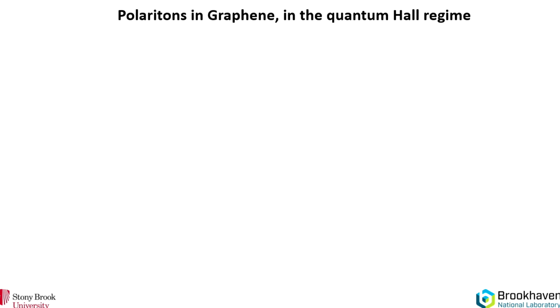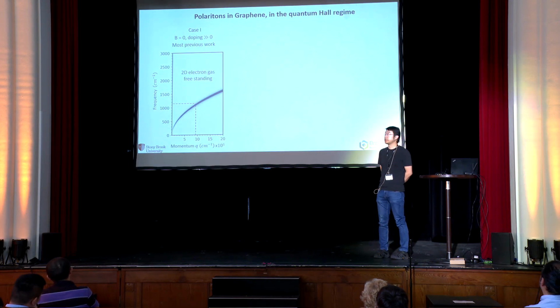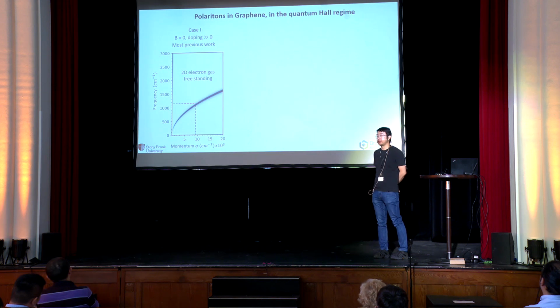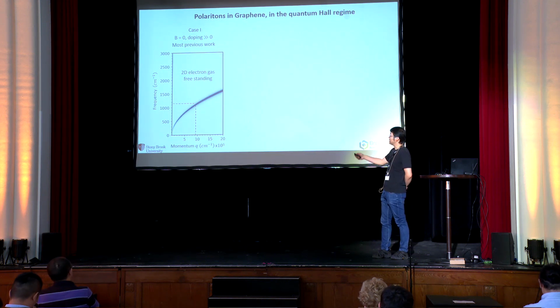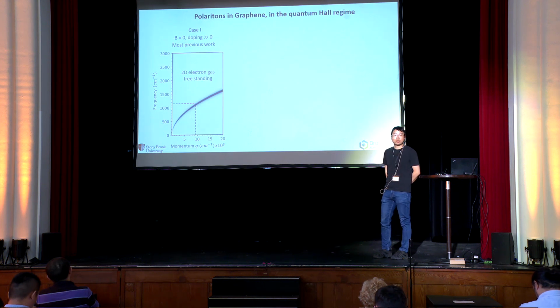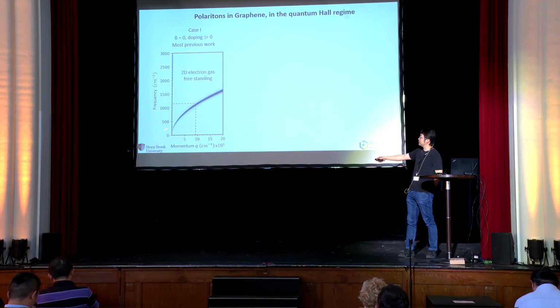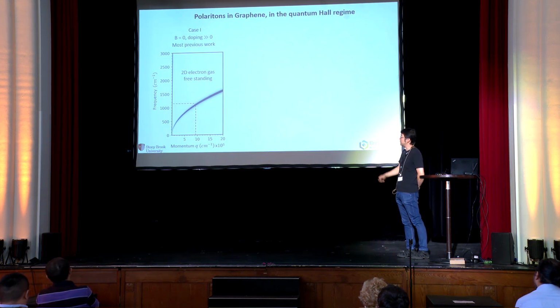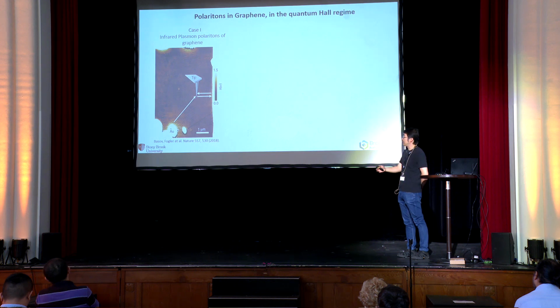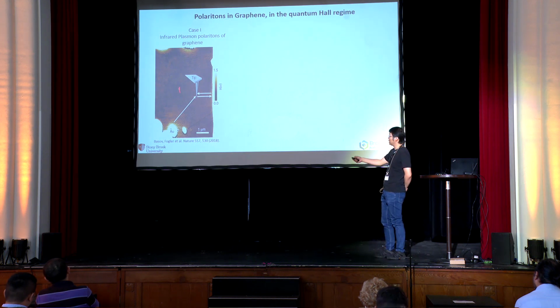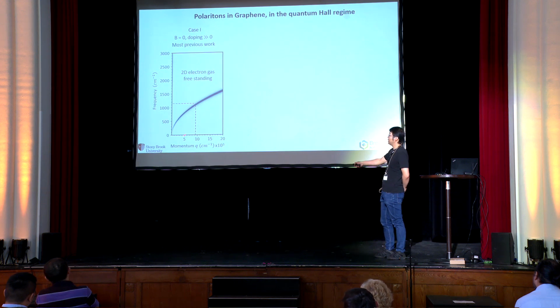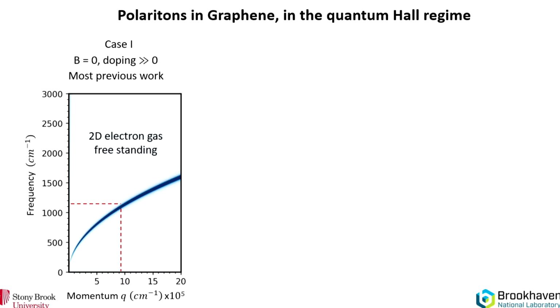So polaritons, we have learned a great deal in the first case of polaritons. I characterize them in 3 different cases, not necessarily true, but this is how I characterize them. One is when B equals 0 and you have very large doping, so you have this plasmon dispersion that you measure with, of course, a near-field system. Of course, Dimitri and Frank and Rainer, they showed a lot of pioneering work on this. I think you all know. But basically, if you have no doping, then this plasmon dispersion will be very flat, right? You won't be able to measure the plasmon dispersion.